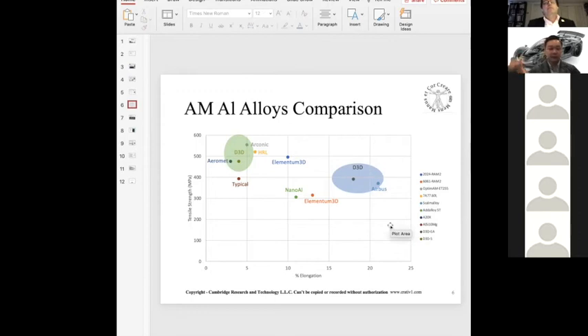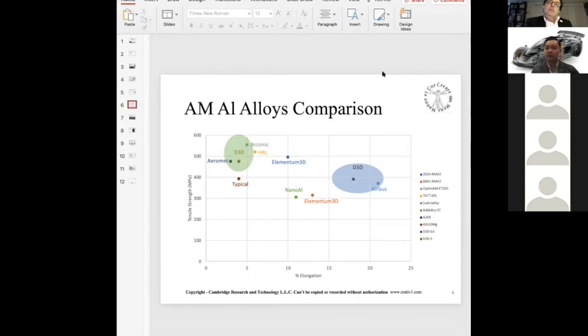Black smoke comes out after you shoot the laser on the powder, and if that smoke is not taken care of correctly before the next laser activates and shoots onto the powder, you get spatter. During our chemical analysis, there are different types of oxides and carbides that are byproducts of the sintering process, and they land on subsequent material. As you 3D print this object in the Z direction, you have these holes or defects embedded in the material, so your mechanical properties are going to drop significantly.